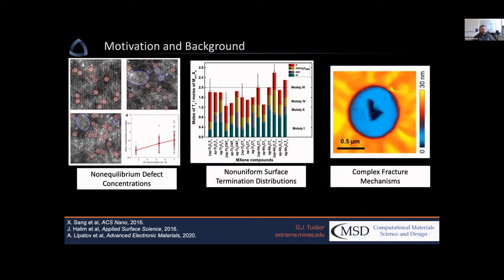And so in that vein of thinking, here's some work where folks have looked at non-equilibrium defect concentrations, very much in line with what was talked about earlier by Professor Rosen, looking at vacancies and looking at the correlation of defect concentrations with how the material is actually processed. Once again, reiterating the point in the middle here that there are non-uniform surface termination distributions. It might not just be one type, there could be many types. And we have to think about that and consider that when we come up with a strategy to probe these fundamental mechanical properties. And then lastly on the right, which is much more aligned with motivating the talk here today, we see complex fracture mechanisms when we mechanically test these MXene monolayers.